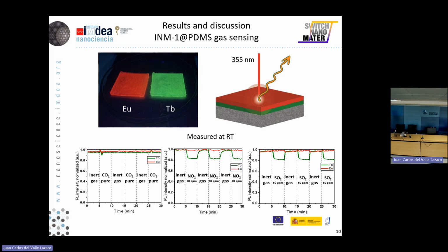the MOFs. In this case, we found that CO2 doesn't seem to produce any modification, so we discarded this gas for this type of sensor. But in the case of NO2 and SO2, we obtain the same behavior as before, where the terbium decreases its luminescence by about 20%, and SO2 shows a decrease of about 22-23%.